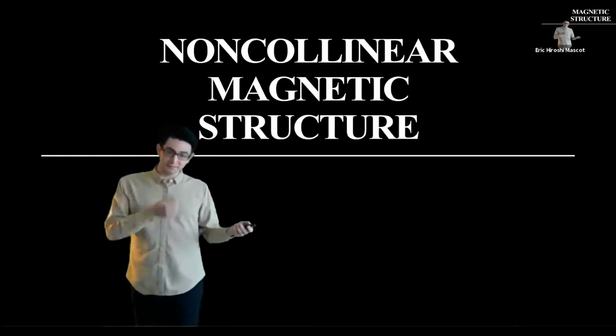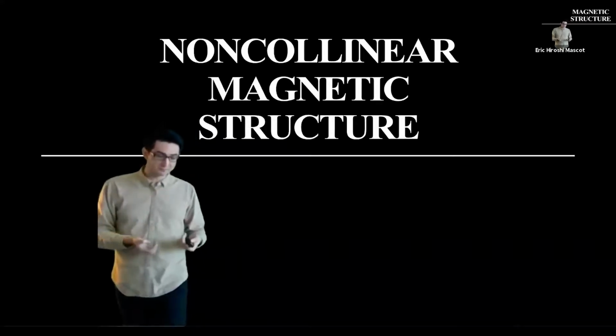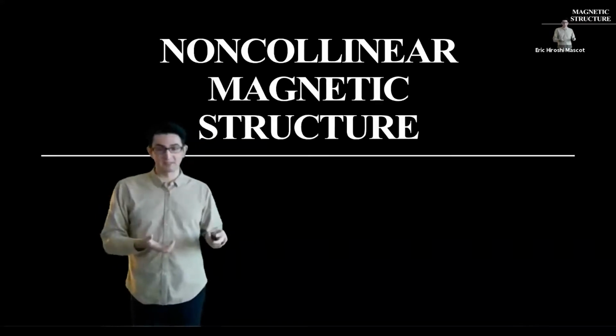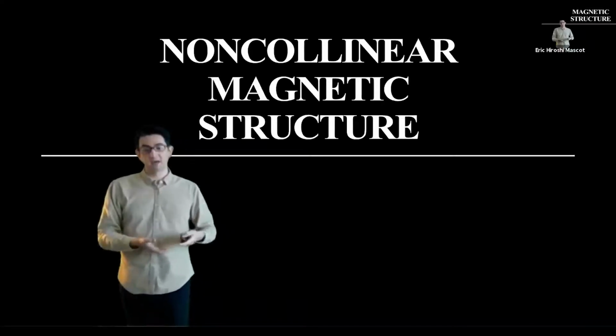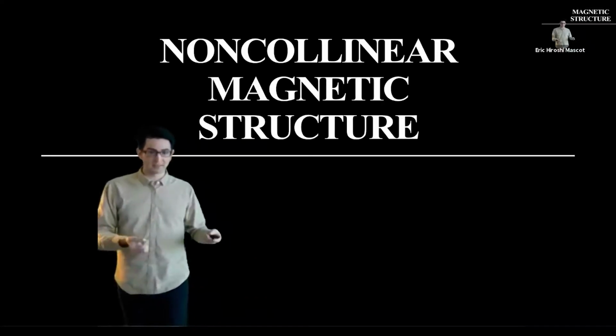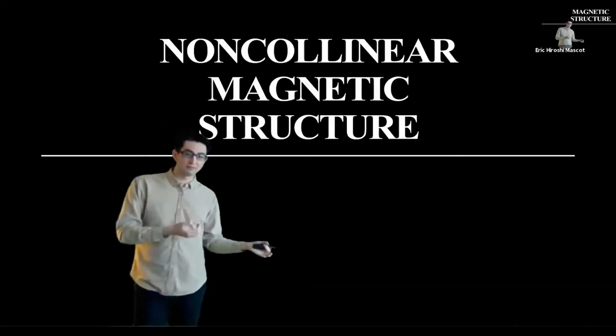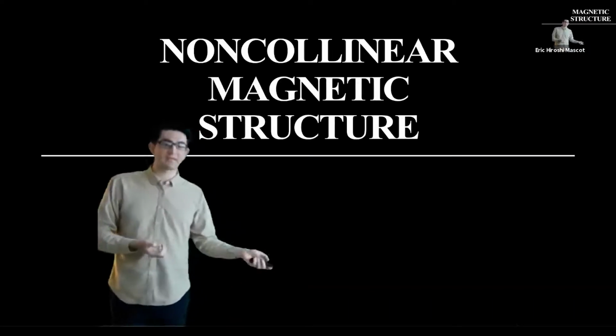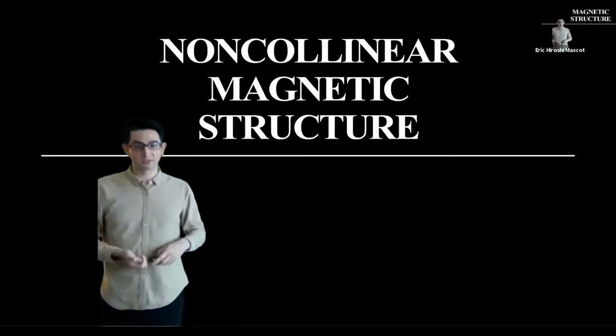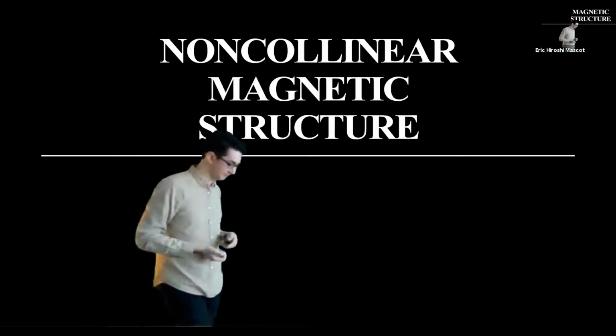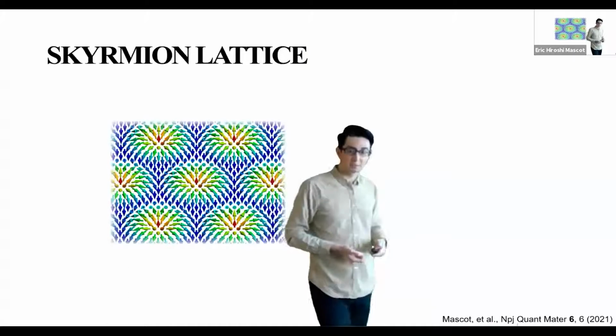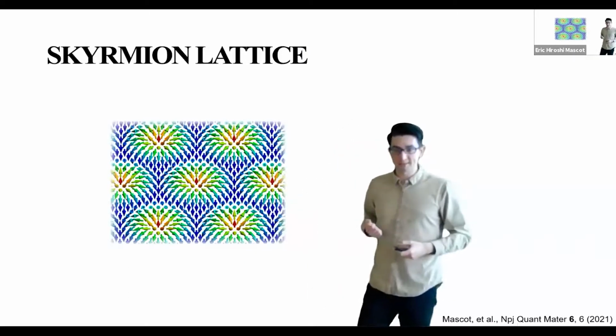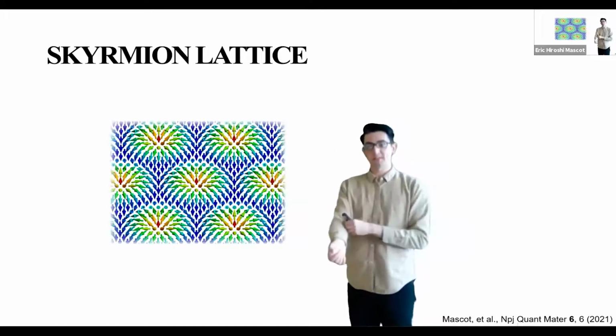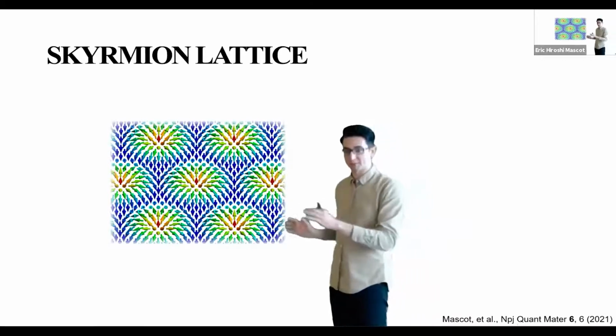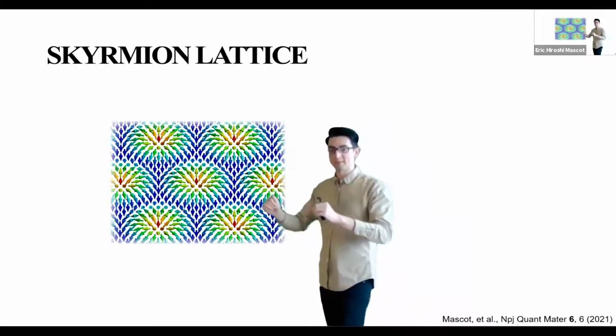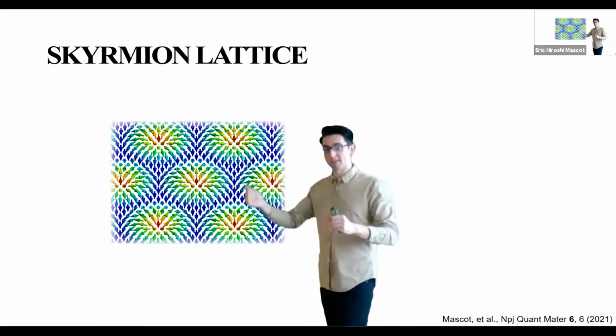And additionally, it requires spin-orbit interaction. And so that limits the different superconductors that we can look at. So instead of having spin-orbit interaction in the superconductor, can we move it into the magnetic structure and still get topological phases? So we look at skyrmion lattices. So this is an interesting kind of magnetic ordering where you have a lattice of skyrmions. A skyrmion has these magnetic moments that rotate from the center outwards.